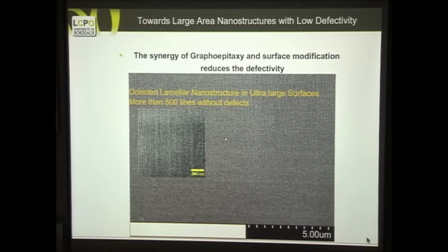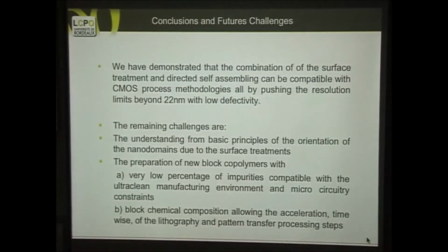In order to do that, and I will not go further on this subject, you have to make polymers that are completely free from metals, because the manufacturing lines in the semiconductor industry don't like to have contaminants and things like that. You have to make polymers that are more compatible with the process of etching and so on and so forth. And above all, we have to make polymers that do not slow down the process, which for this kind of features to appear, so far needs 1 hour of annealing with a solvent at high temperature, but you have to do it in a few seconds.